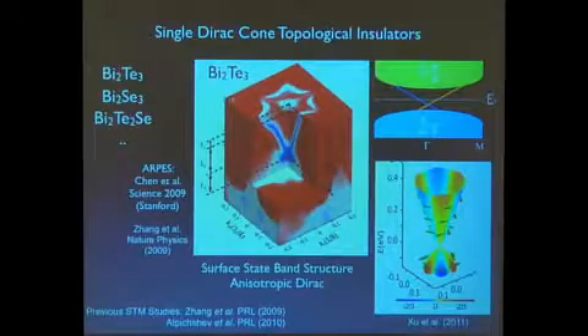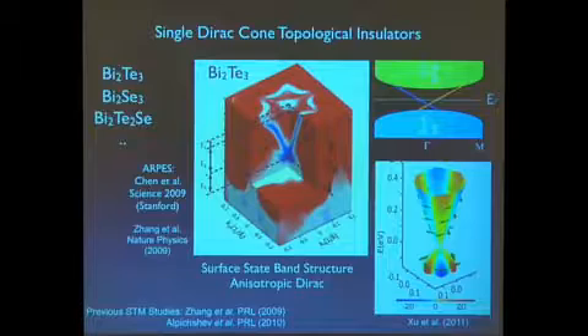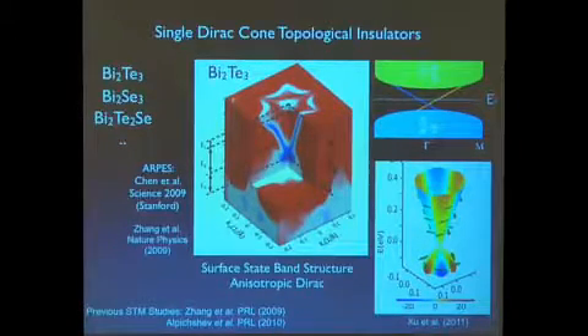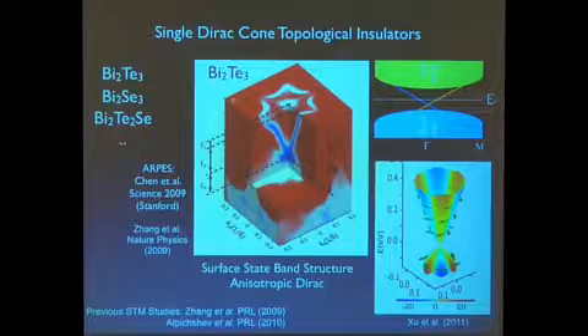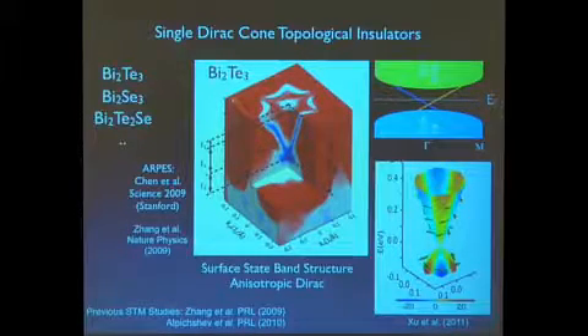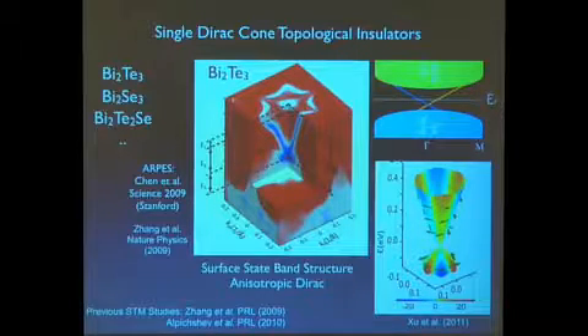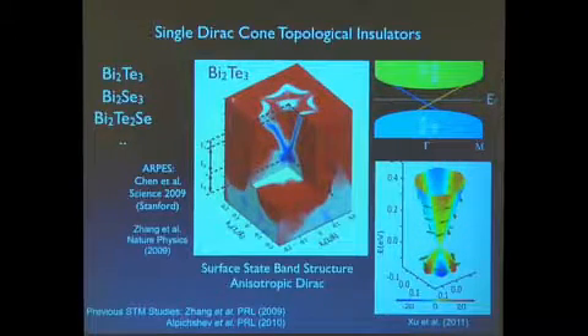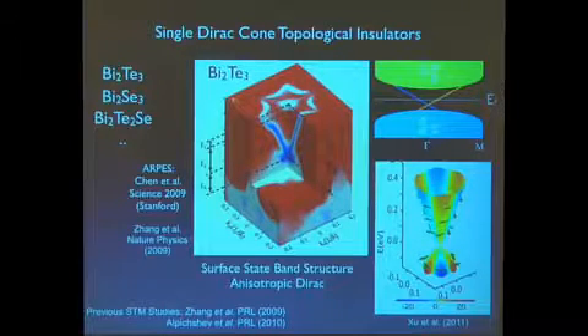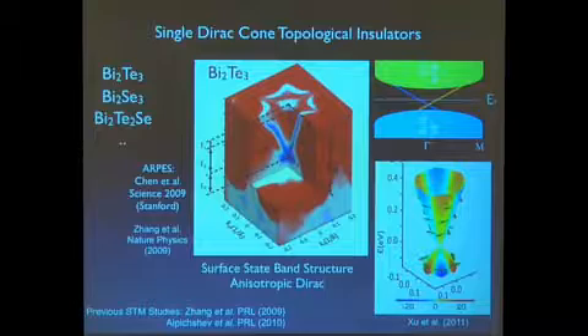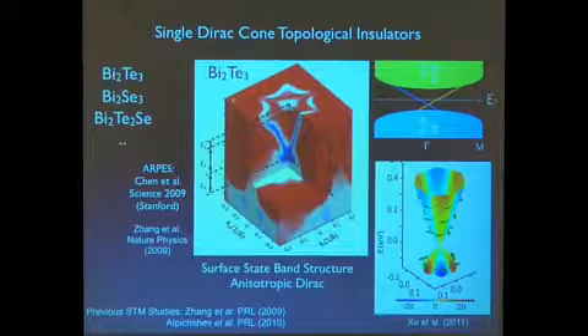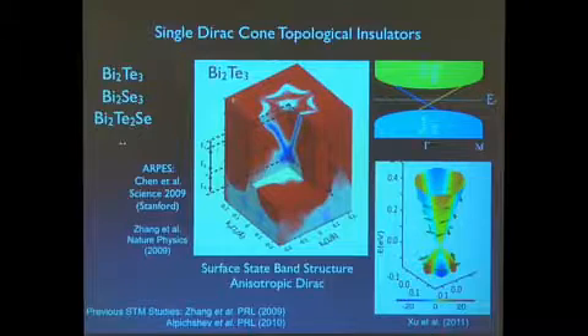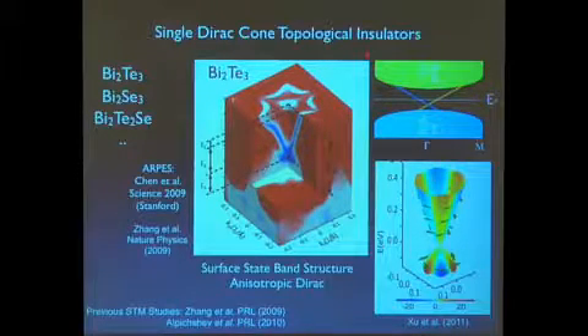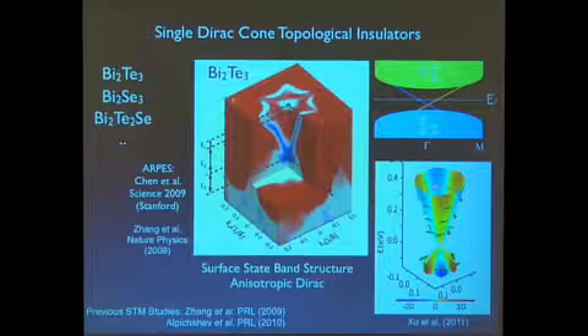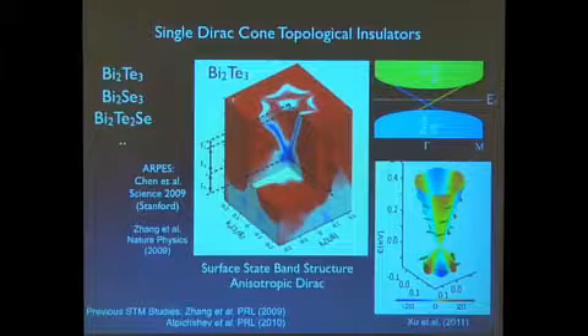So what this establishes is the fact that you have no backscattering in this particular compound. But let me say that the number of topological insulators now has grown to many, many. There are hundreds of compounds. And nowadays, the focus is on those topological insulators in which the structure of the electronics of the surface state is very simple. In particular, it is Dirac-like E versus K behavior. So instead of having 3 or 5 crossings, here you just have one crossing in the chemical potential. And again, you have the same spin texture, if you like, associated with the electron momentum being locked together.